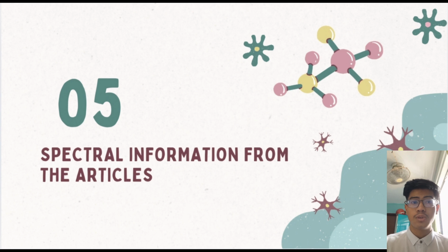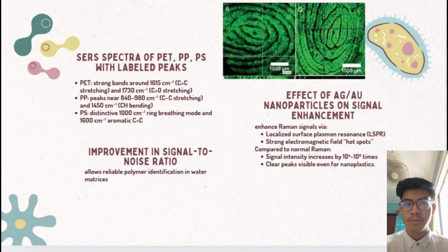Now, I move on to the spectral information reported in the literature using surface enhanced Raman spectroscopy. The SERS spectra show clear and characteristic fingerprints for common microplastics such as PP, PET, and PS. For polyethylene terephthalate, strong bands are observed around 1615 inverse centimeters, which correspond to C=C stretching, and 1,730 inverse centimeters associated with C=O stretching.